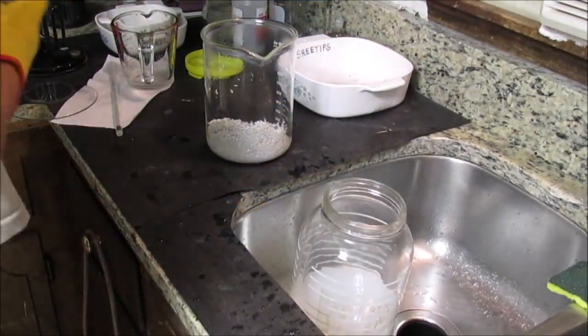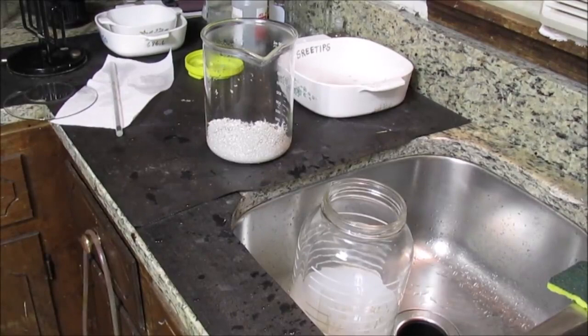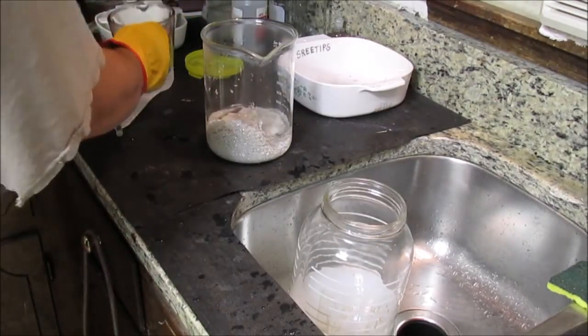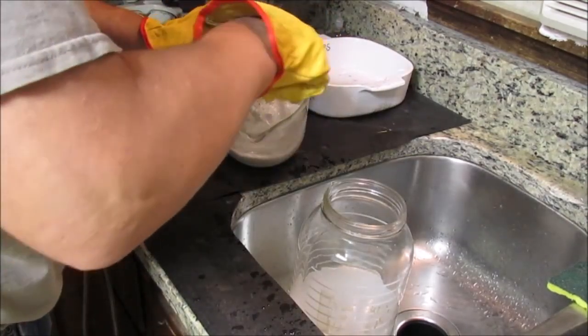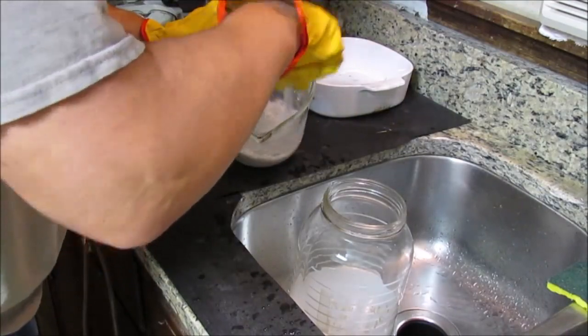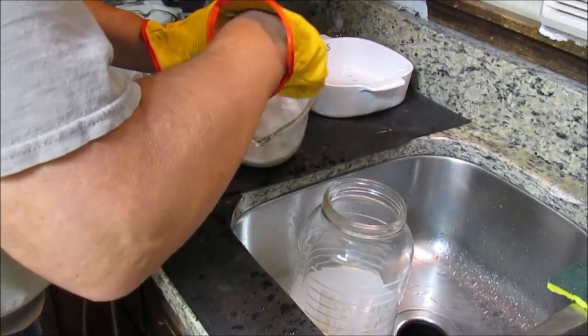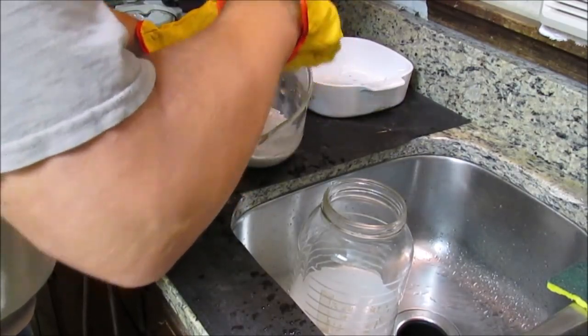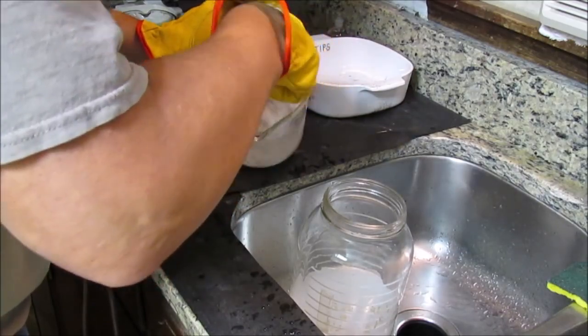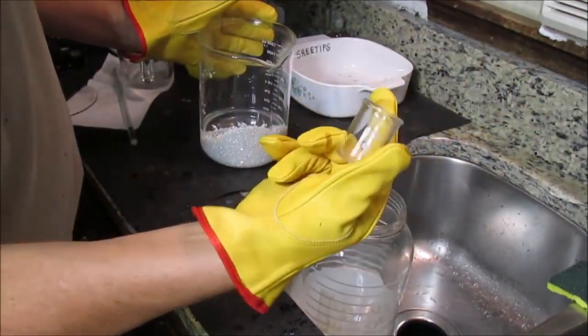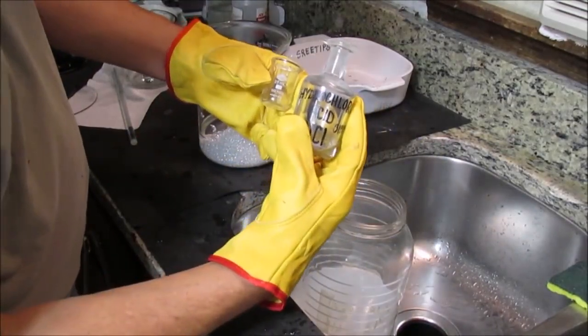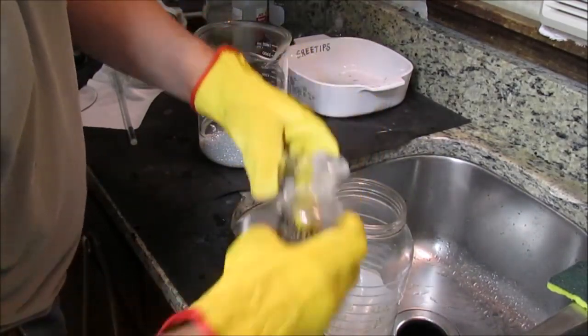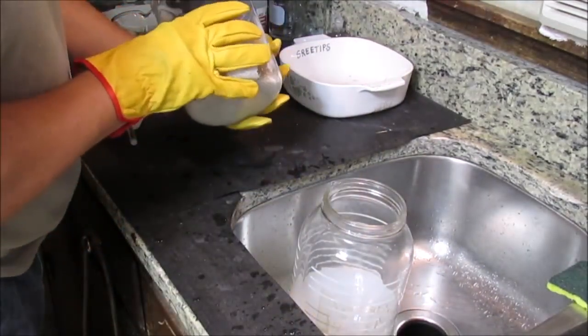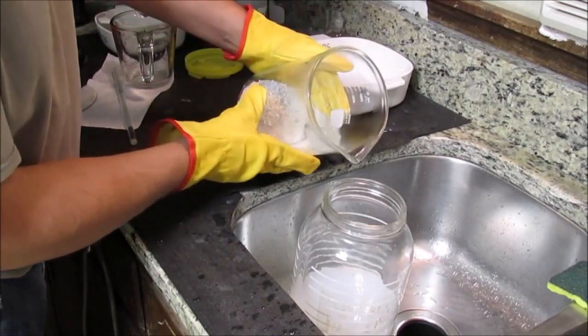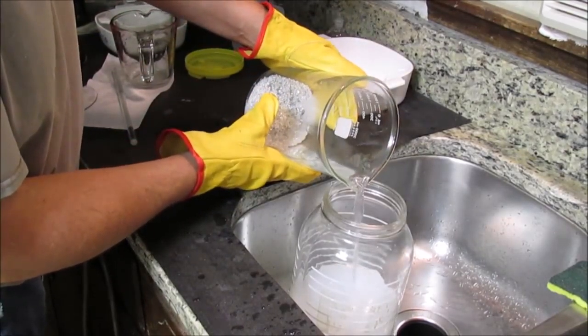Okay, this will be the third rinse with hot distilled water. This time what I'm going to do is take a little sample in this small beaker here, and then add some hydrochloric acid to it and see if we precipitate any silver chloride. If we do, that means we need to continue rinsing. If we don't, we'll rinse one more time just for good measure, and then we'll go ahead and dry out the crystals.